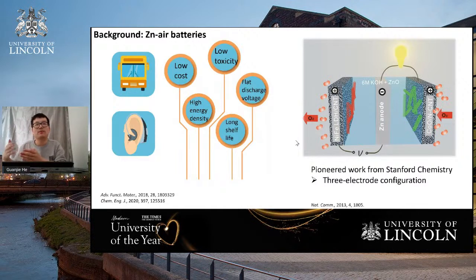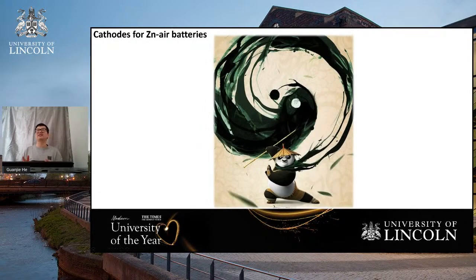But those are not for practical use. For all of our batteries, that is 2 electrodes, right? We don't need to change the electrodes during the charge or the discharge. But it is quite clear, right? In order to realize rechargeability, we need the oxygen reduction catalyst and also the oxygen evolution catalyst in one system. And actually, oxygen reduction and oxygen evolution conflict with each other because they are reversible reactions. This is like the Chinese ancient philosophy, yin and yang.